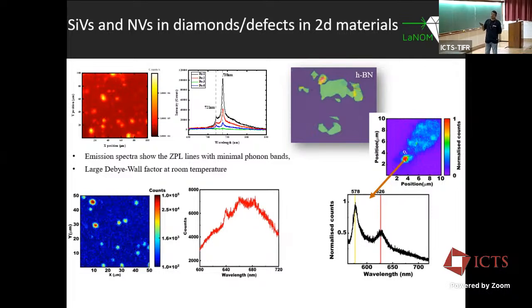We got this sample from our friends, and we measured it in our lab, and we could see that the zero phonon line is around 739 nanometers. And most of the phonon sideband is gone. So this is a quite interesting system without much phonon contribution. And recently we also started measurements on hexagonal boron nitride, where you have a 2D material.